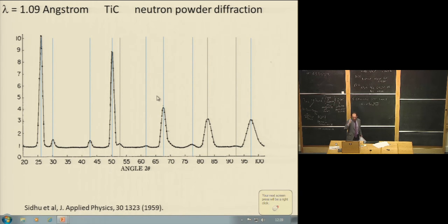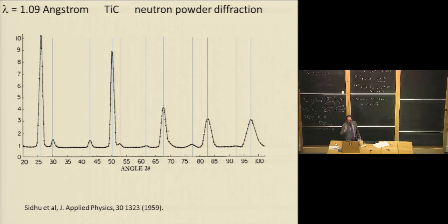So yes, you can tell it's FCC without doing any calculation, because of the pattern that you can sort of imagine that if this is 3, this is 4, then there's a big spacing to 8, then a little spacing to 11, 12 close together. So you can kind of see that the spacing is the right spacing for an FCC lattice.